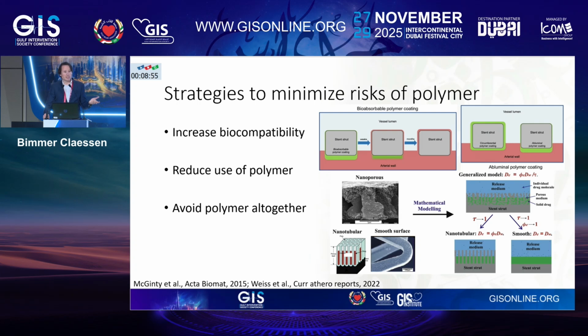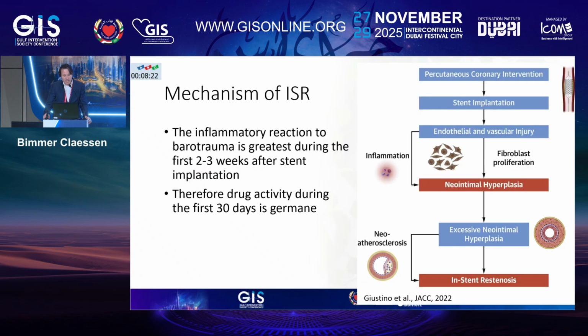Now, another approach may be to use a bioresorbable polymer. So the polymer is on the stent, but it gets resorbed slowly together with the drug, and then after a couple of months, you basically leave behind just a bare metal stent. And another strategy was to only coat the stent on the abluminal side with the polymer and the drug. And that way you avoid contact between the polymer and the blood vessel, while still having contact between the drug-eluting stent and the vessel where the drug can be eluted. The final strategy is avoiding a polymer altogether. However, that has a few engineering challenges, as we will discuss right now.